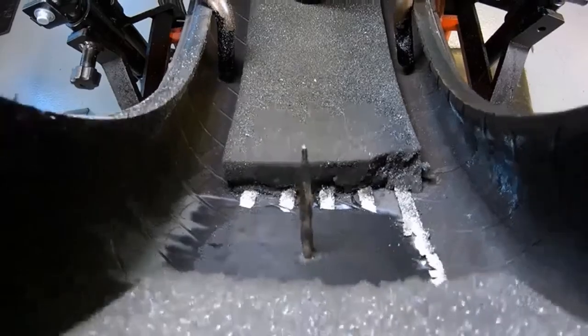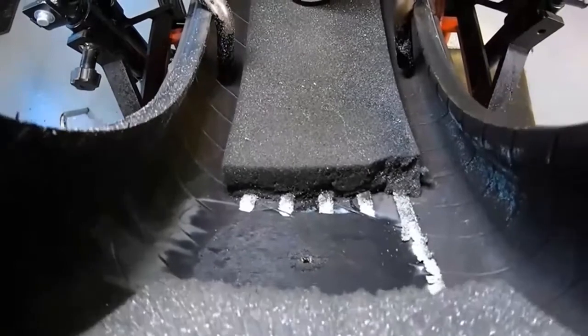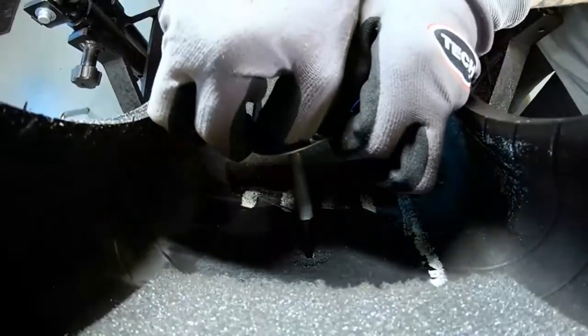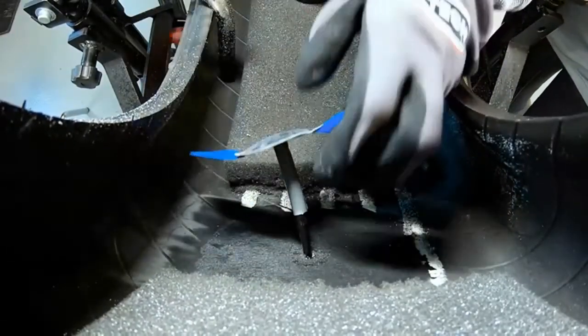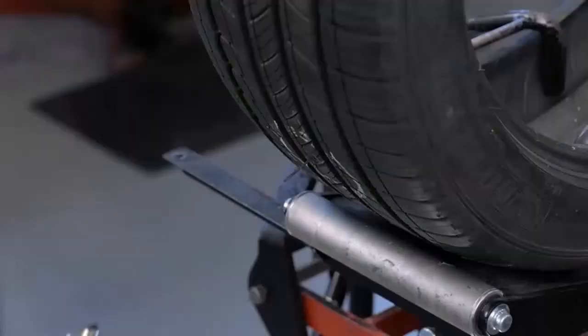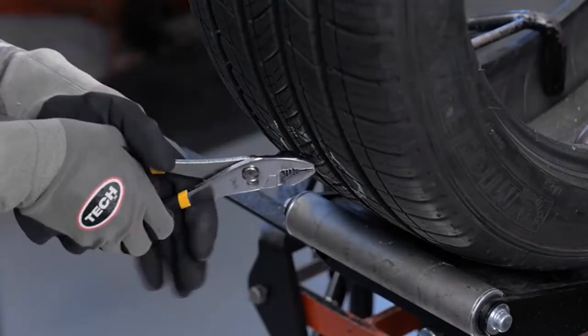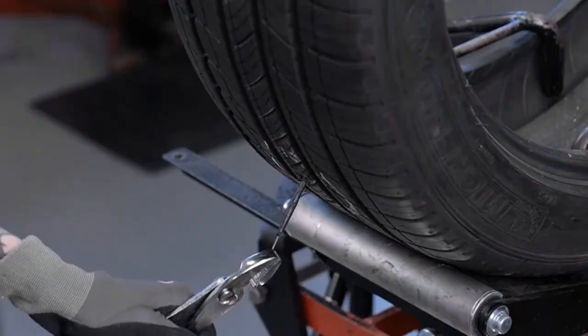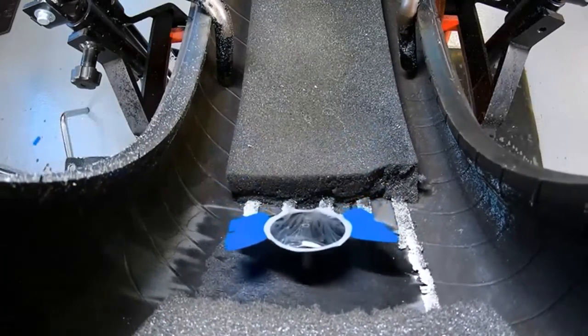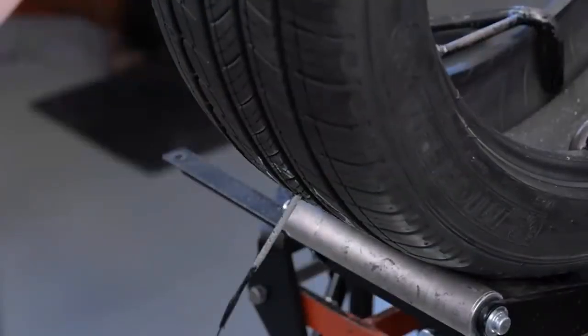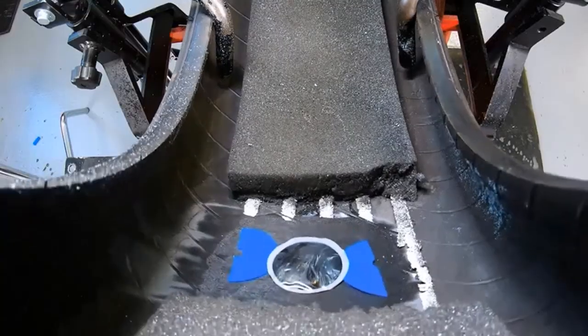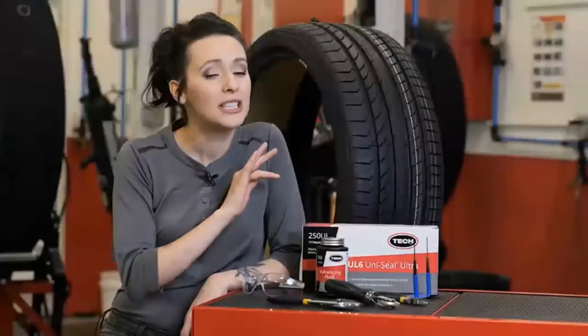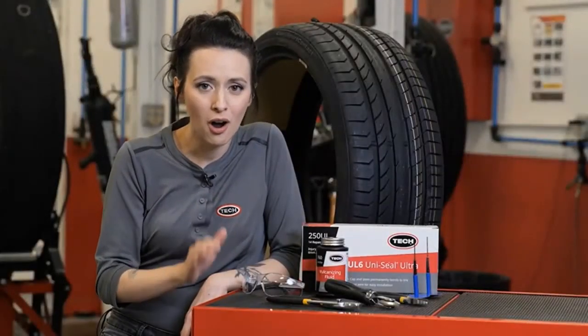If you're using a tire spreader, be sure to relax the tire beads to prevent what is known as bridging of the repair unit. Bridging creates areas where portions of the repair are not making full contact with the tire's inner liner, and this can lead to premature failure of the repair. You may now remove the spiral cement tool, then feed the lead wire of the Uniseal Ultra into the injury from the inside of the tire.